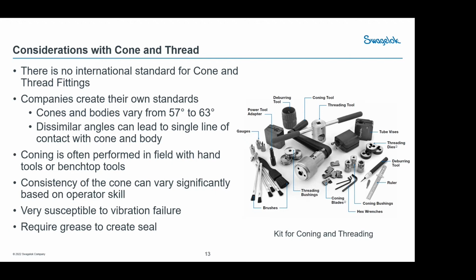Unlike having it on rigid, process controlled machines with process controlled tooling, what you end up having is a whole bunch of random possible variables coming in, including chipped tools, including chatter, including putting oil on the parts that are needed to be able to thread and getting chips in the way. So lots of different things can come into play that can cause issues without getting very consistent coning onto the parts. One of the pieces that can cause an issue is if the collar is not put on properly, it can lead to not getting enough load into the actual fitting to get a seal. So consistency on making them up can be a problem.